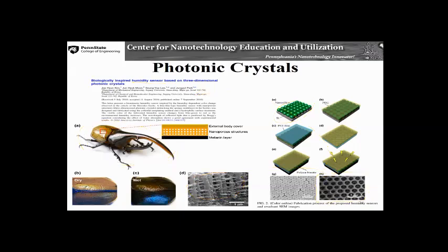So in a very similar way, the photonic crystals here, they reflect back the blue color while they do not touch the other part of the spectrum, okay? The blue color gets reflected back when there's humidity. What is happening when there's humidity? These holes are, up to some extent, filled with water. Do you guys see that? So it would again change its refractive index. So its refractive index no longer is 1 inside those holes. And overall, the response of the photonic crystal will change. When there's air inside the holes and when there is water inside the holes, humidity will change its optical response.